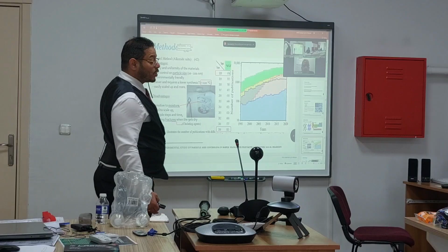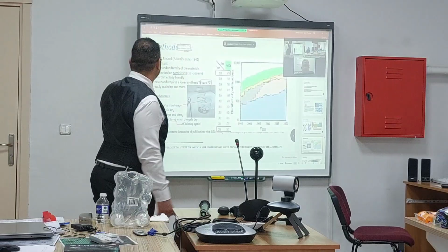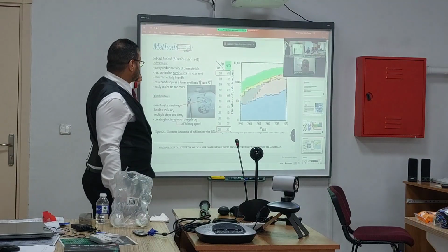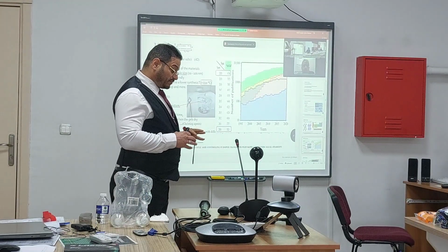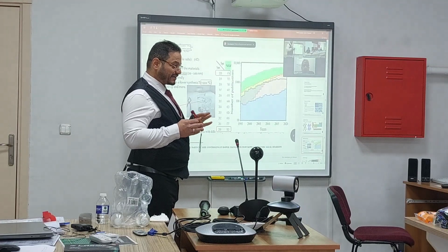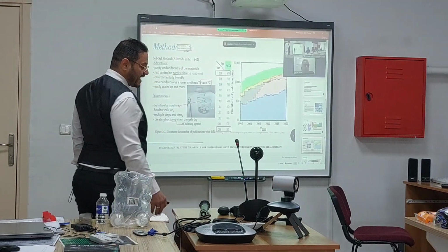First, the advantages are purity, uniformity, and full control over particle size, which can be from 10 to 100 nanometers. It is environmentally friendly, not toxic, and easier to acquire. It can be done at approximately 200 or 220 degrees, and it is easy to scale up.